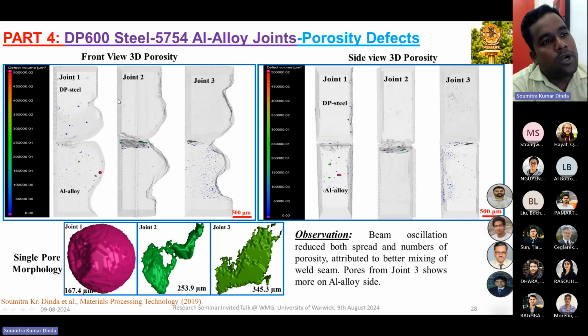This is because when we were welding this set of materials, we did not pass our electron beam at the junction point. We offset the beam towards the aluminum side by 1.5 millimeter to melt the aluminum and restrict the steel melting, so that we can restrict the intermetallics formation. We did this based on some literature study, some experience, and some trial and error.